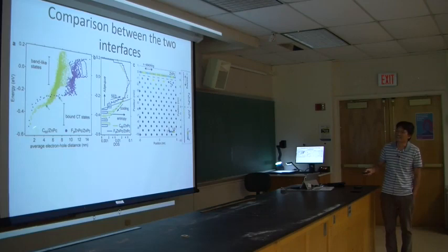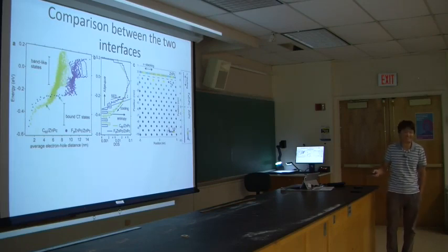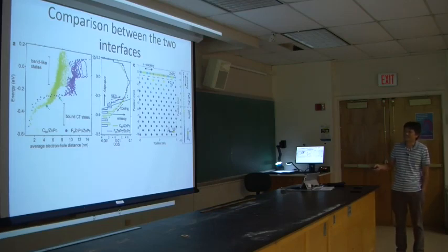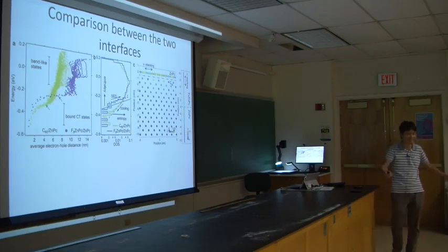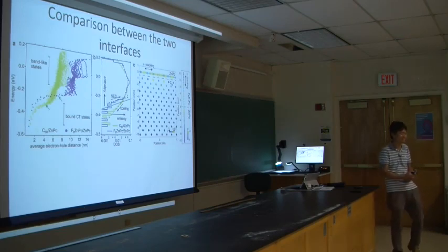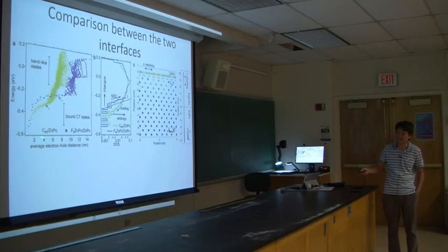So here are all the eigenstates that we find. These are energies, and each of these dots is an eigenstate. And then these are the average electron-hole distances, okay? Now these states are clustered around 0 eV, which is basically the band-like state. If you have a delocalized electron, you form this band, right? So basically the width of this band is the electronic coupling between different sites. And then of course we have a tail here, which corresponds to the bound CT states. These states have lower energy. It's exactly the Coulomb interaction term, right? As the distance between the electron and hole becomes closer, your binding energy becomes bigger, right?